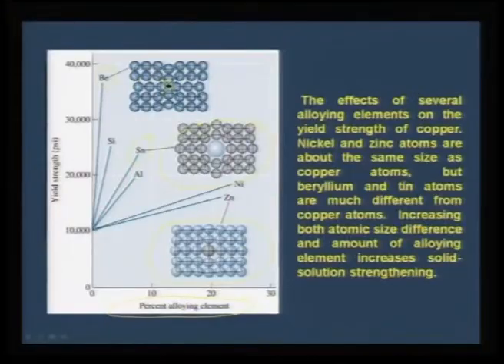For example, even though there is a lattice expansion or lattice contraction, you would see as a function of yield strength of these alloys, beryllium doped copper system seems to have a better yield strength or a very high yield strength compared to tin, compared to zinc. So, even though we have a good solubility limit up to 30% for tin in copper or zinc in copper, based on the nature of the metal, the size of the metal, you can actually see the yield strength is differing considerably. So, this is the solubility limit for all these three compounds, but you can get a maximum yield strength for beryllium only around this composition, maybe up to 20. For tin, we can extend up to 30.